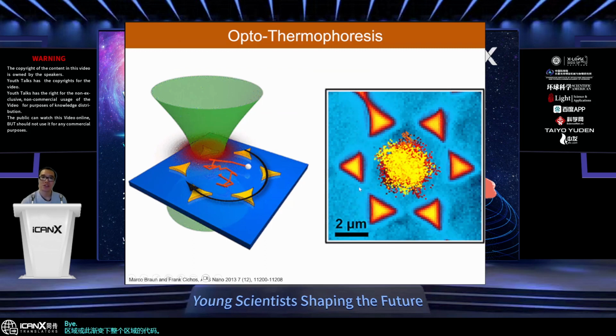But the challenge with the thermophoresis effect in optical manipulation is that in many cases, the movement will typically be from hot to cold region. But in a lot of cases, the position irradiated by the laser beam becomes hotter. So you would think that the laser beam actually pushes the particles away rather than trapping them.